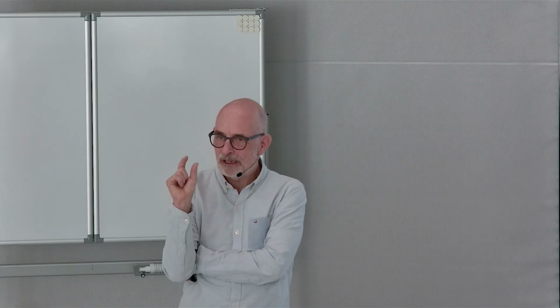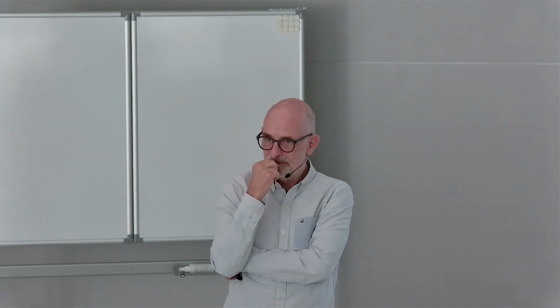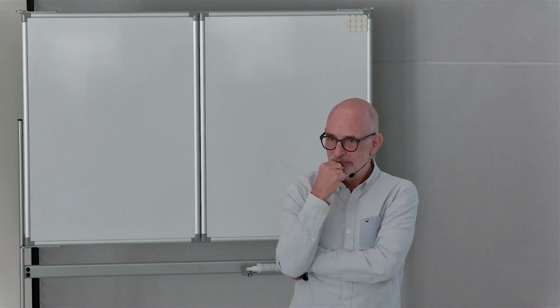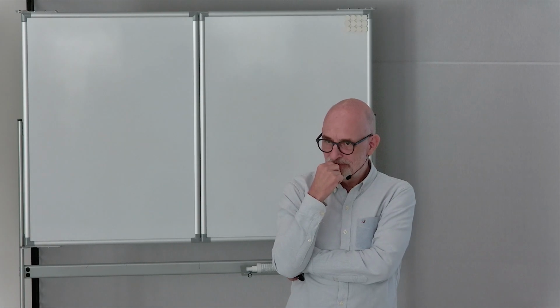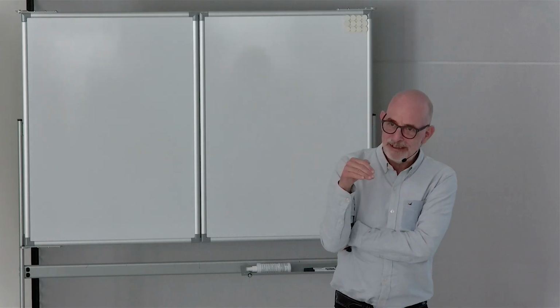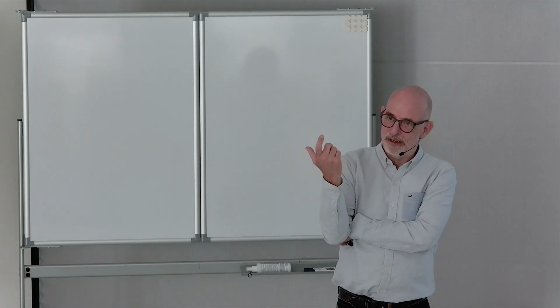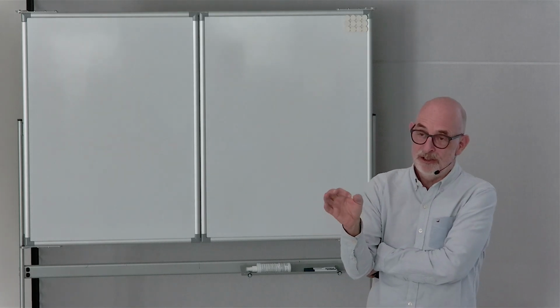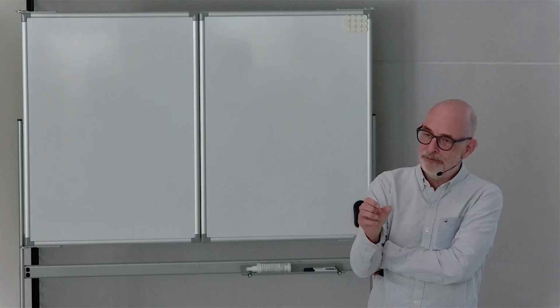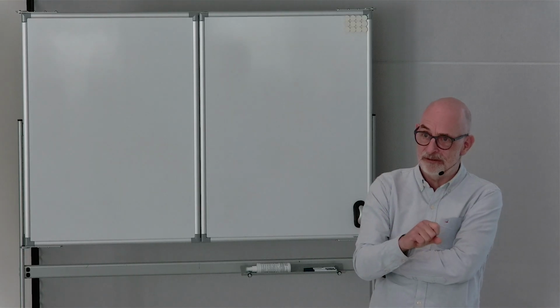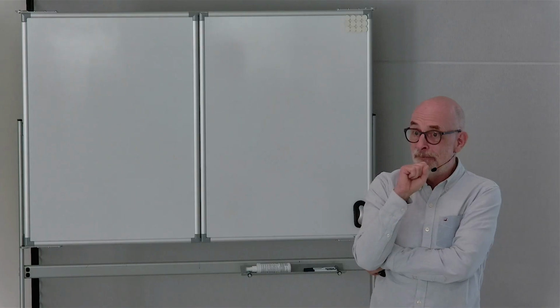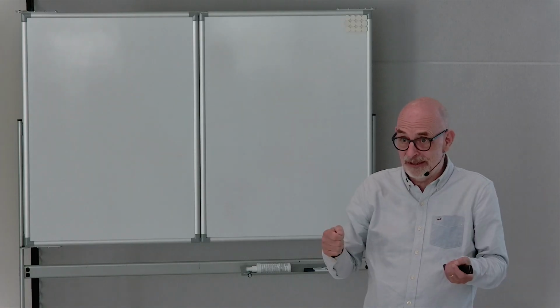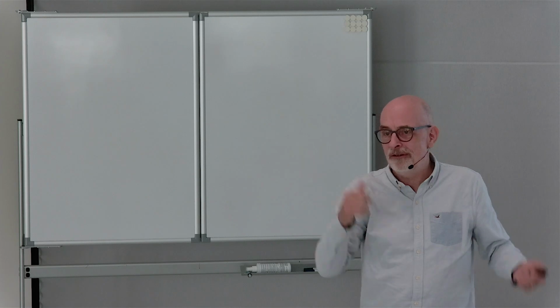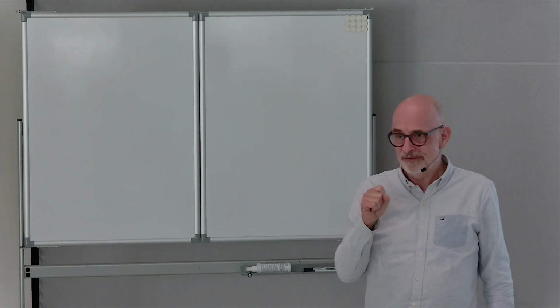So you're talking about the electronic wave function in real space in the quantum dot. Yes, exactly. Like that p orbital that we have as an image, for example, what would be the difference between these two, the first two electrons that you're filling, K and K prime? So I cannot give you a precise number, but from the Coulomb charging energy, you can calculate the size of your quantum dot. And we know that the extent of our electronic wave function is around 20 nanometers. And obviously the P state will be more extended than the S state, but I can give you a rough estimate, but I cannot measure it.